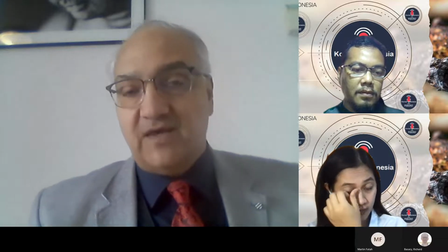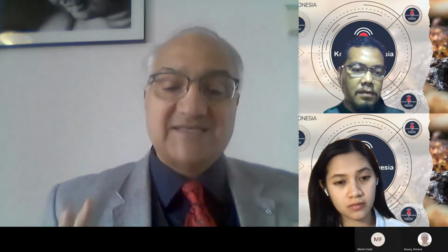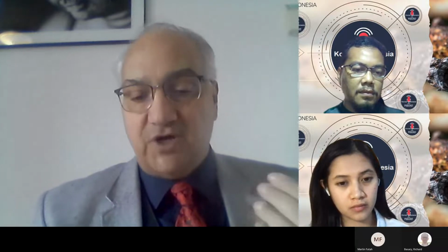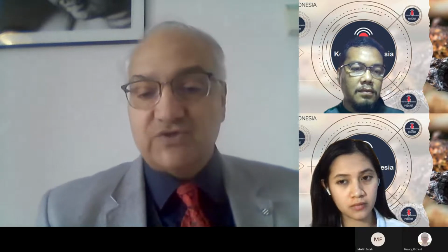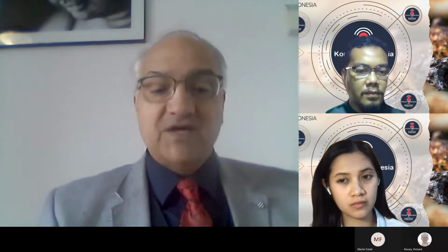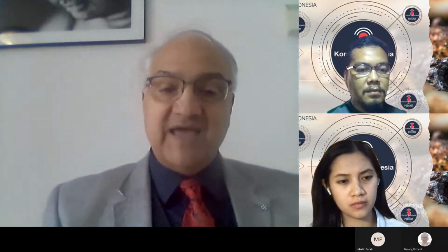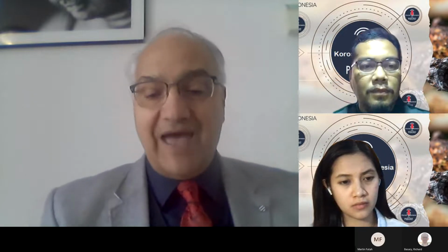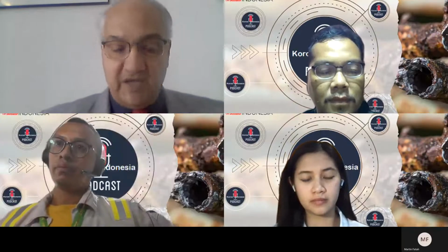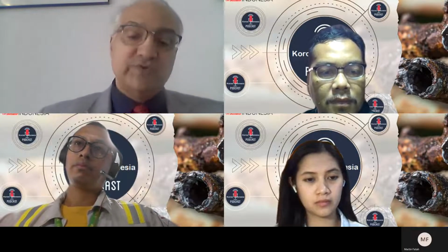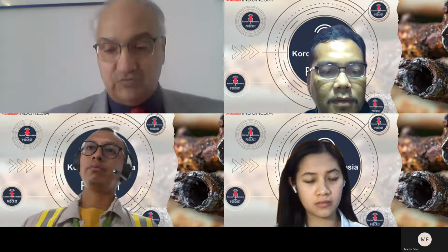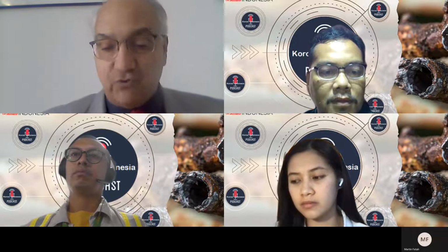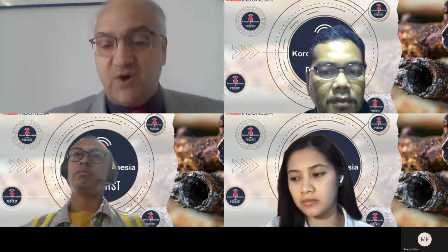When you have factors that can facilitate or assist this electron travel, it means that corrosion becomes faster. One of these factors is the action of bacteria. Why? Because bacteria, like us human beings, need energy. And in order to produce energy for themselves, they need electron transfer so that they are able to turn food into energy. These electrons that are used by certain bacteria happen to assist corrosion, and what we see is then called microbial corrosion.